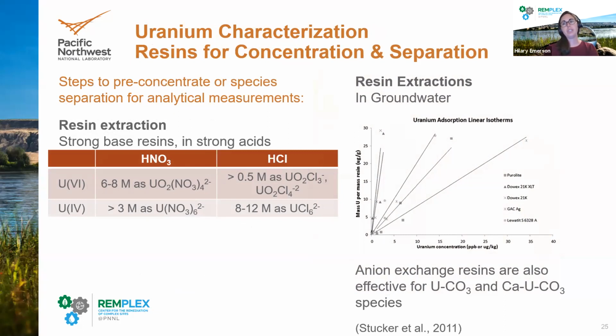So we can employ some physical methods, such as manganese oxide co-precipitation, but we can also take advantage of some of the great anion exchange resins that are out there. And as an example, we can use some strong base anion exchange resins to separate uranium in strong acids by forming uranium nitrate and uranium chloride anions. And there are also some that we can use for separation of uranium in groundwater by taking advantage of those negatively charged uranium carbonate and calcium uranyl carbonate species that form. And as you can see here in this figure, we get very good separation of uranium with this Dowex resin, just as an example.